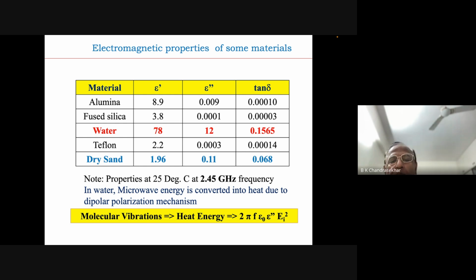But with microwave, because it penetrates deep into the material and gives rise to uniform heating, the whole thing can be done in less than 30 or 45 minutes. What takes 2 to 3 days can be dried within 1 hour or half an hour, depending upon the size of the core.